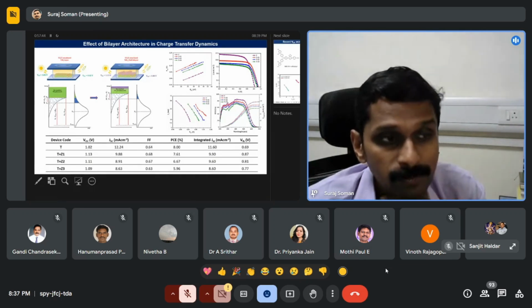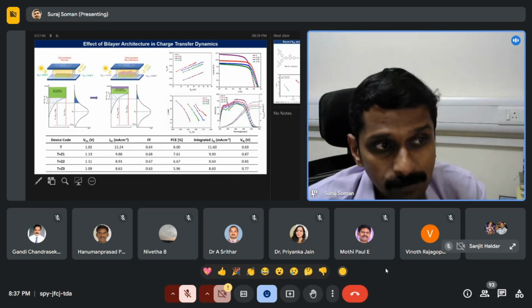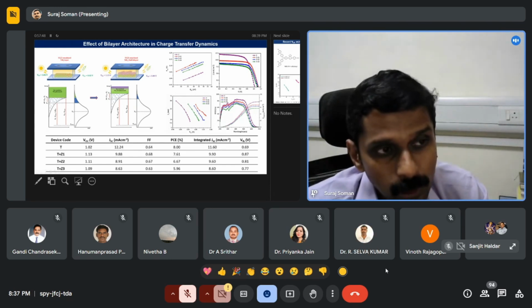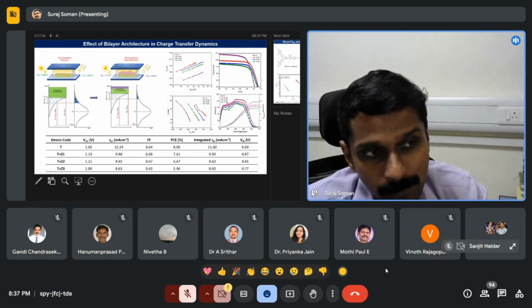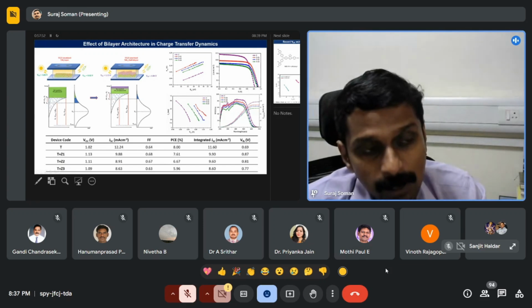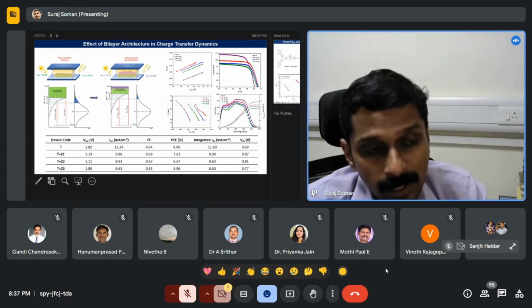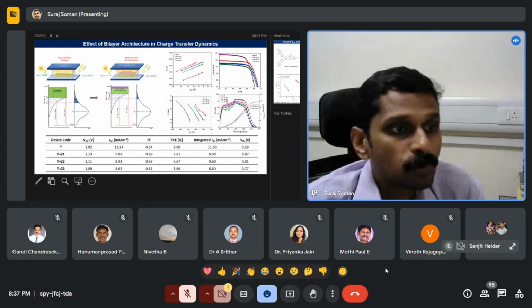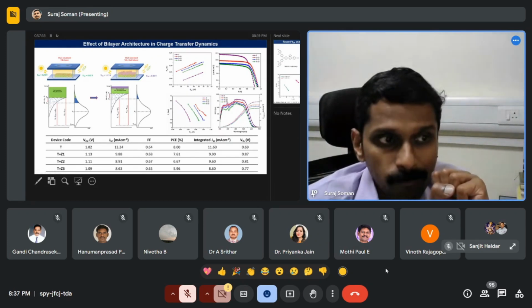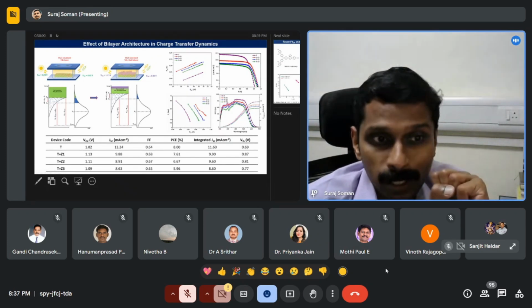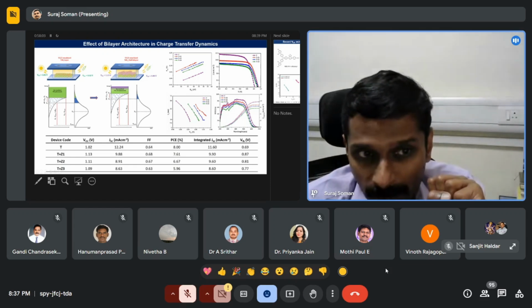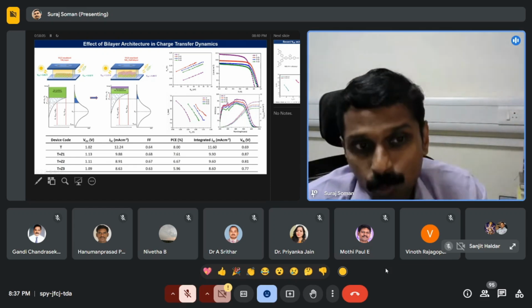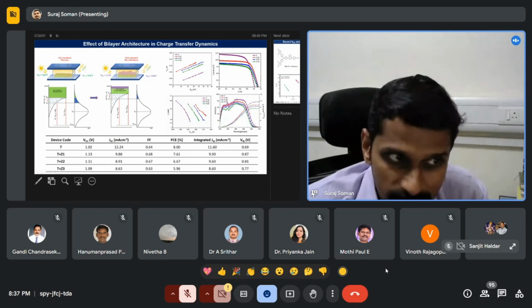And there what we have seen is that this negative shift in the conduction band actually pushes the trap states and the surface states far away from the energetic band gap which actually comes from your electrolyte systems out there. So that actually prevents the recombination. Thereby, you are having a far better improvement in the lifetime that reflects in the performance.